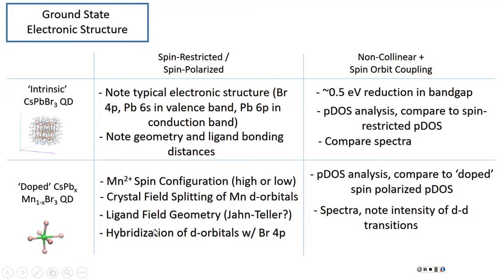So you get the level splitting just from the symmetry, but I also see hybridization of the d orbitals with the bromides, and even hybridization of these with themselves. So I kind of have to sort through all of that mess too to nail down what's actually happening in the system.